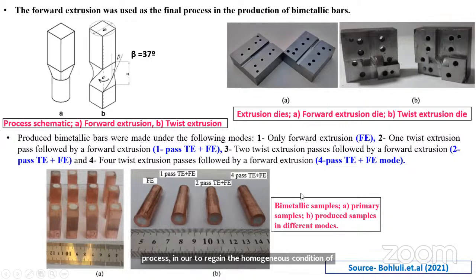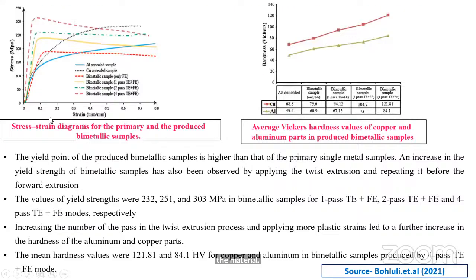You can see the effect of what happens. This is the stress strain diagram. The blue color is the annealed sample. You can see the strength of the annealed sample is less when compared to the bimetallic sample processed with 4 pass twist extrusion plus 1 forward extrusion process. The strength ranges from 300 to 350, then it goes on decreasing from the center to the end. This is the strain. You can see the strain of the samples. This is the Vickers hardness.